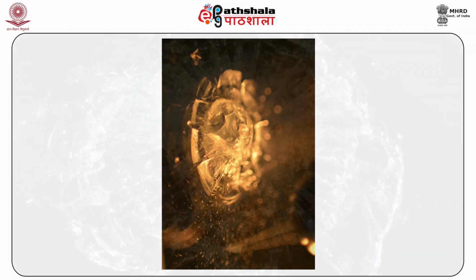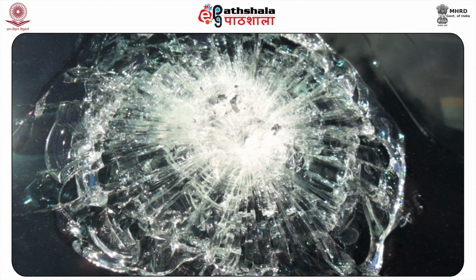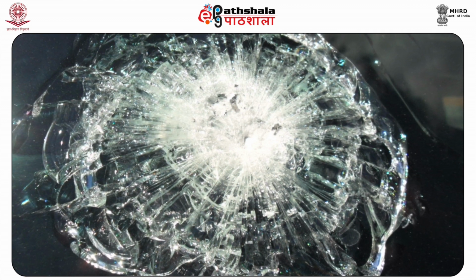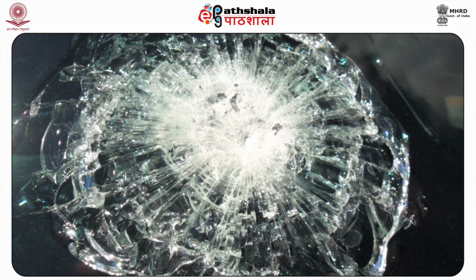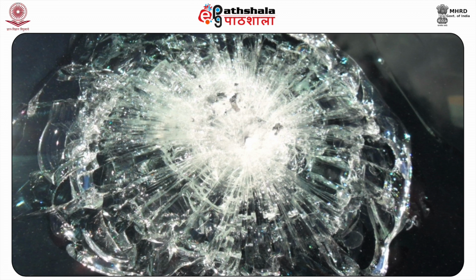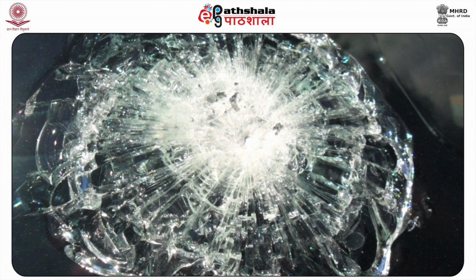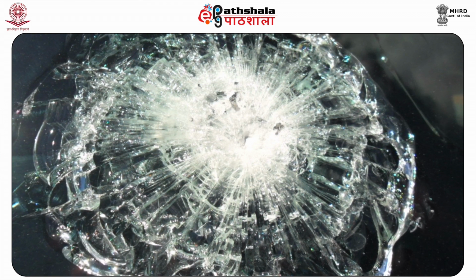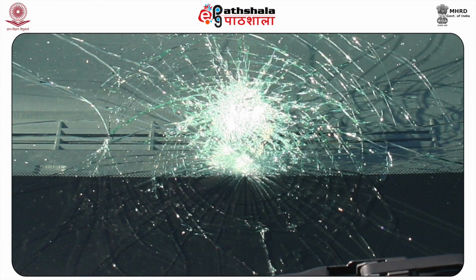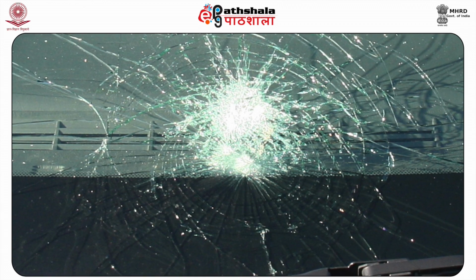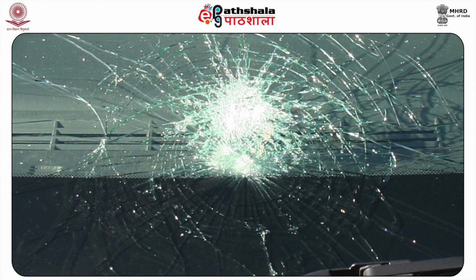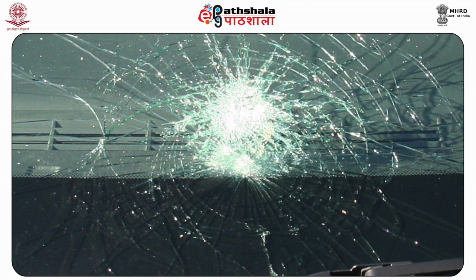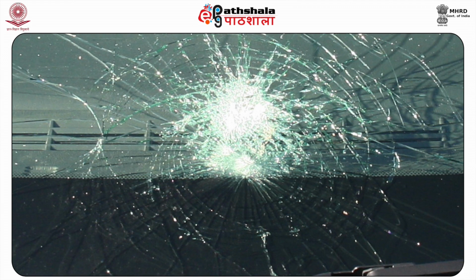Projectiles that pass through the glass at an angle to the surface produce an elongated hole. Radial cracks may also develop from high velocity impact. The sequence of multiple impacts can be deduced when the cracks caused by a subsequent impact terminate at previously formed cracks. Thermal fractures. In non-tempered glass, a typical heat crack is curved, has a smooth edge, and has no indication of the point of origin of the crack.